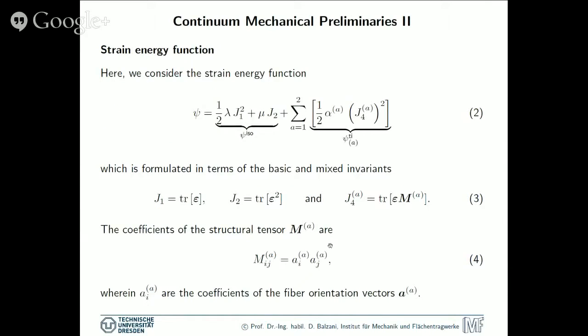Here we focus on, or let's say the particular strain energy function is given. So that's the specific form of the energy function that we consider here. It is decomposed into an isotropic part describing the matrix material and the superposition of two transversely isotropic parts that account for the individual fiber reinforcement. So that would be the transversely isotropic energy associated with one fiber A. So A is the summation index from one to two. Material parameters in here are first the Lame constants here and this additional elasticity parameter alpha, which captures the elasticity in fiber direction. So basically the one responsible or associated with the collagen fibers.